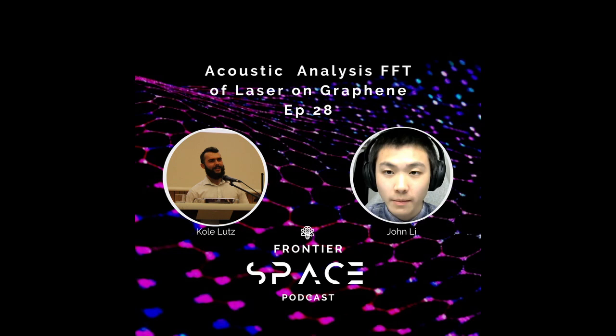Well, so basically laser-induced graphene, depending on how you're forming it, has many different properties. For example, previously we were able to show that by varying the laser parameters, by varying the conditions under which we laser, we get very different properties. So here we are able to now use sounds to either analyze what is being formed there, or as well as make sure that if we want a specific product, to ensure that the product is actually what we want to form at that location. So the thing about it is that for applications such as electrocatalysts, or for battery electrodes, or for microsupercapacitors and things of that sort, you want specific morphologies of laser-reduced graphene to form.